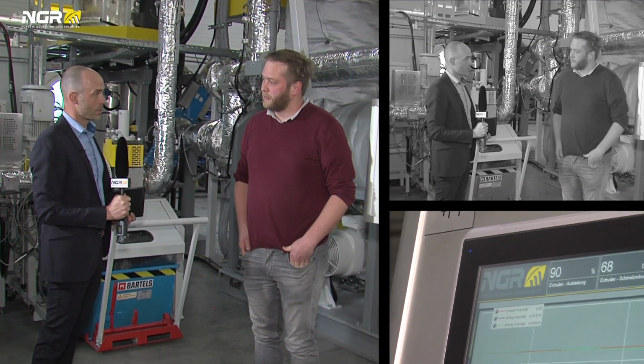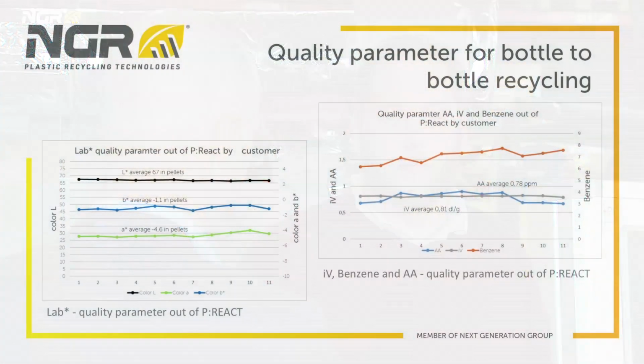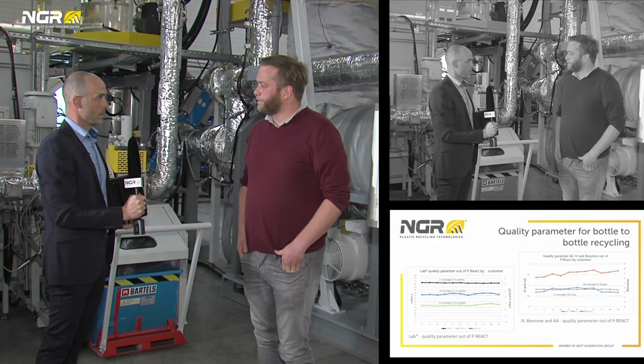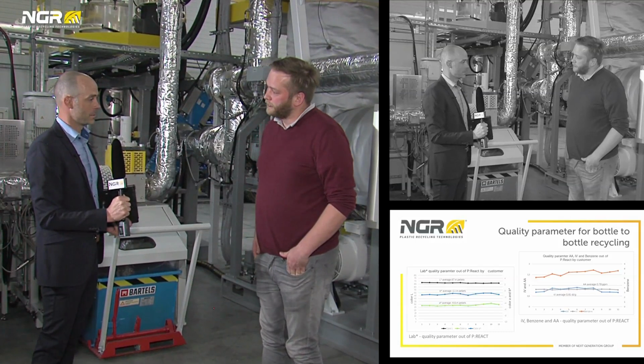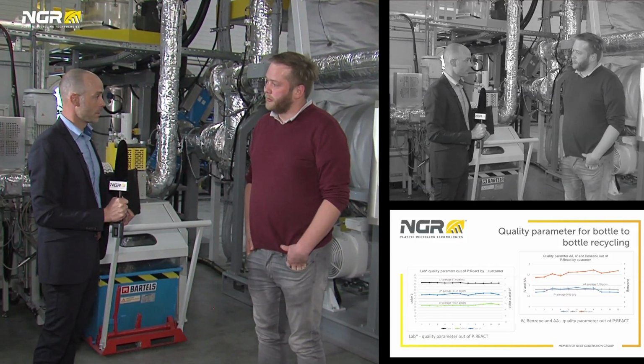Daniel, do you also have some results from a trial we ran in a production plant? Yeah, as you can see here, the b* is below 0 at all times with a still very high L*, and the volatiles such as benzene and AA are very low, with 0.8 in AA and 7 ppb in benzene. So the very low benzene is really an amazing number. This is really unique.